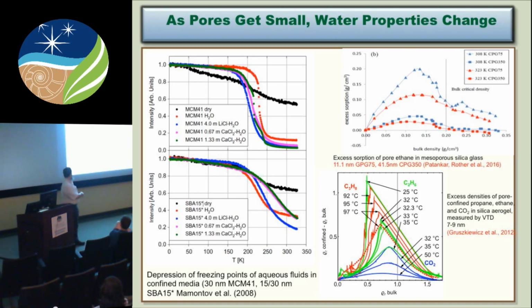What happens as the material freezes, those motions stop, and the elastic intensity increases. So essentially what you're seeing here is the freezing point. And that's the basic point right here. About 200, 225 degrees is the freezing point of water confined in MCM41, which has about 30 nanometer pores. So, 50 degrees, ballpark, below the standard freezing point for water.